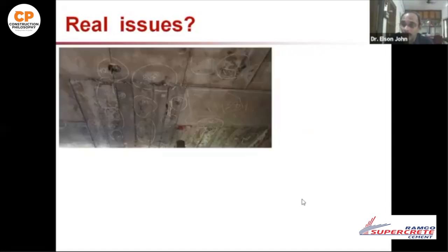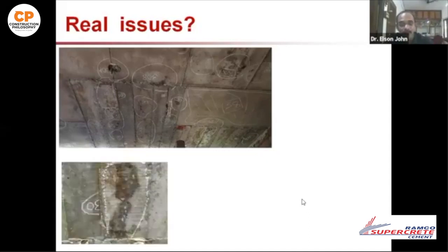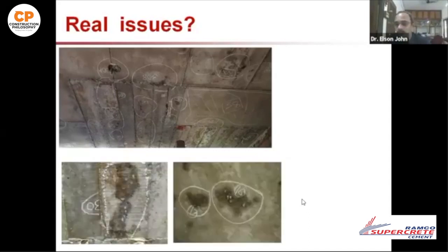In an actual structure, you can see lots of cracks when you go into the field. I will show you a picture from a recently constructed building in Cochin. It's a 750 square feet flat, and they have drawn very nice pictures. It's not an artwork. They marked 68 cracks on the bottom side with chalk and numbered them, you can see 37, 38 like that. And on the top surface they found almost 130 cracks, mainly because of disturbance and plastic shrinkage cracks. Some of the cracks are extending through the concrete, and you can see the water percolating through the line cracks into the defective areas.